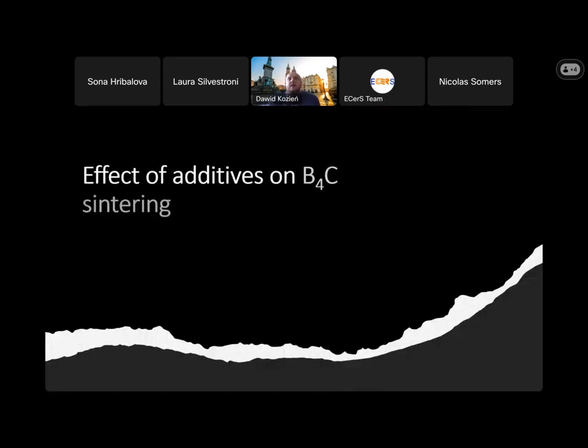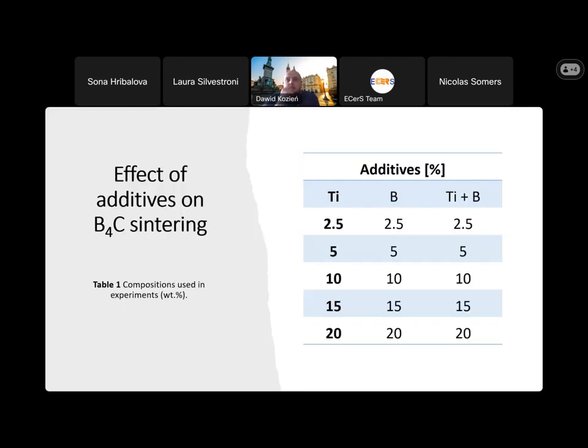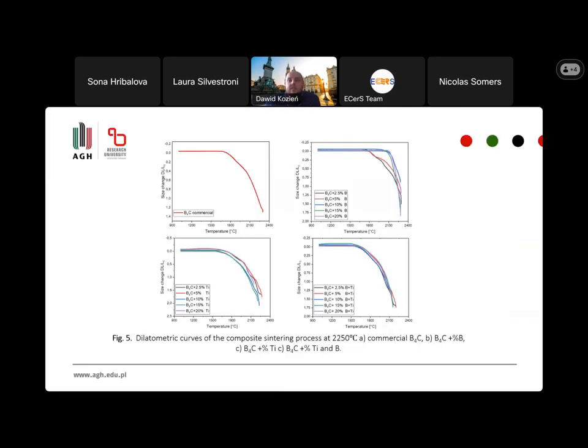So the next part was the effect of additions on boron carbide sintering. Let us assume maybe we can change something. We can add titanium, boron, and titanium with boron. We have better density, and we assume that titanium will go to titanium diboride. So we start the composition with commercial boron carbide with additions of 2.5, 5, 10, 15, and 20% of the additives. And after that, we see how the synthesis temperature changed.